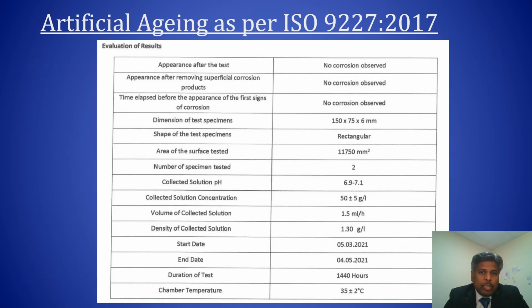The next few slides will show the testing that was done as per ISO 12944 part 6 for a C5 high environment, and you can see that the results were quite outstanding. It was exposed to 1440 hours of artificial aging as per ISO 9227, and the results were that the coating system was able to withstand the corrosive environment, the accelerated testing as well.